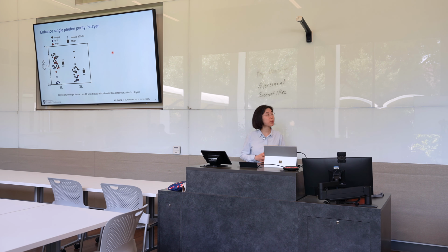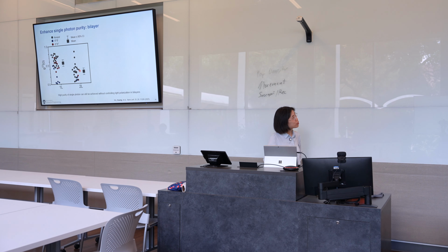So overall, if we summarize the G2 measured for monolayer and bilayer, we can see for bilayer, you can relatively easily achieve lower G2. And for most of these results, they're without polarization control. So we can still achieve high purity single photons without controlling the light polarization. And a simple solution here is just to use bilayers.